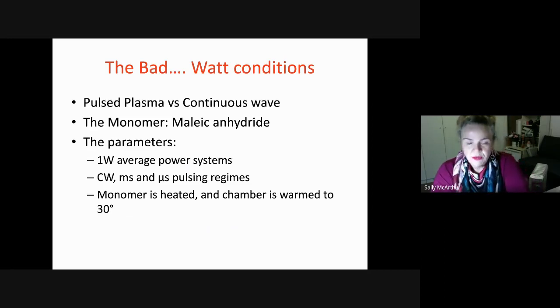And what we do in this system for maleic anhydride, we have chambers that are metallic, so we have to heat the monomer because maleic anhydride is not particularly volatile. And then the chamber is just warmed slightly so that we don't condense the monomer onto all the walls of the chamber at the same time.